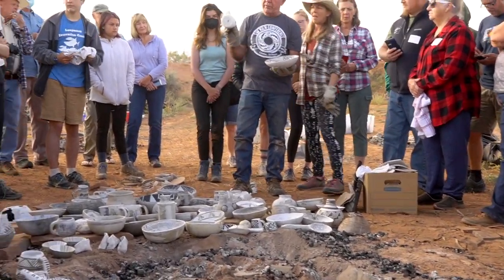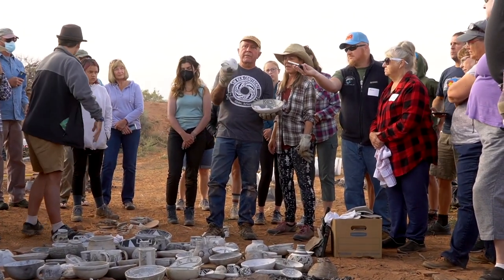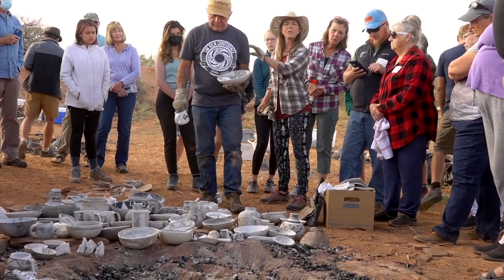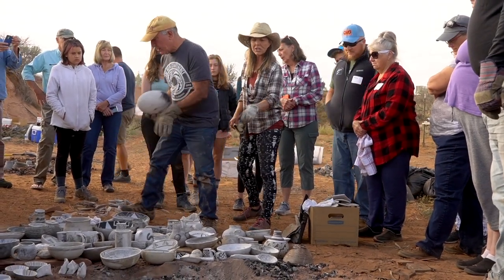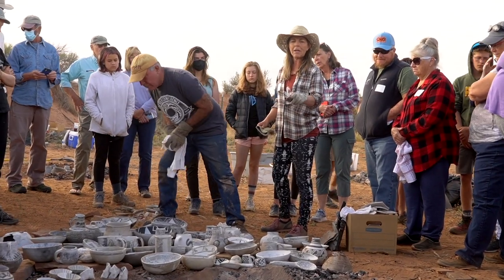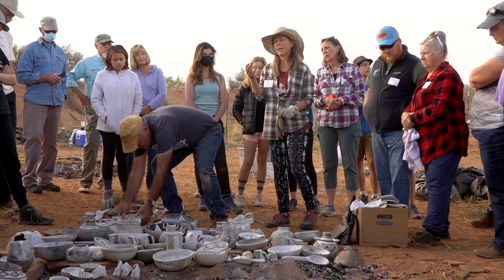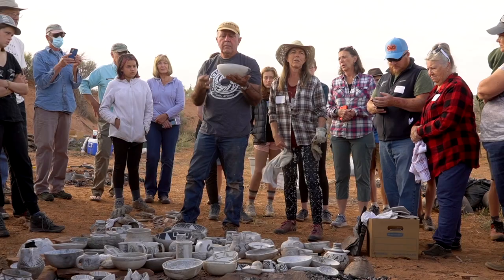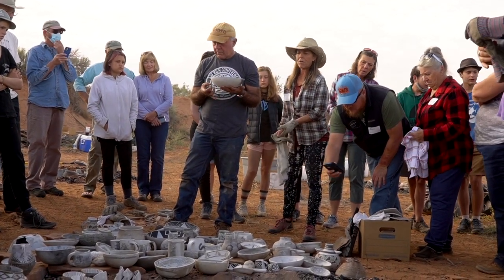This is Cherylene and Tori's paint, and this is my paint. So I suspect there's probably something else going on. Right, because that is like more sulfur. Crystal clear. And don't forget, his paint is loaded in sulfur, because I've fired his bowls before where the ash is literally bright yellow. So if you tie that up with any alkali in the kiln, wherever it's coming from, you'll get a crust on them that you can't get off till you hit about 1200 Celsius. So calcium and sulfur together are not your friend.